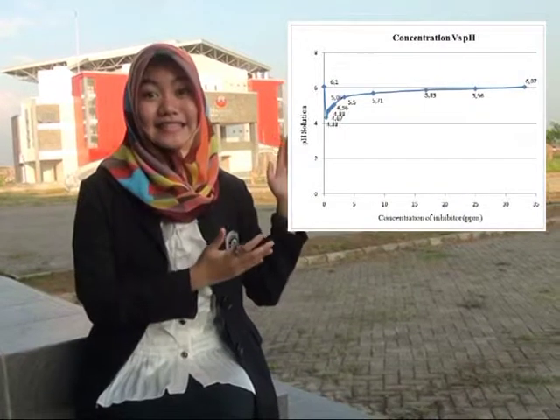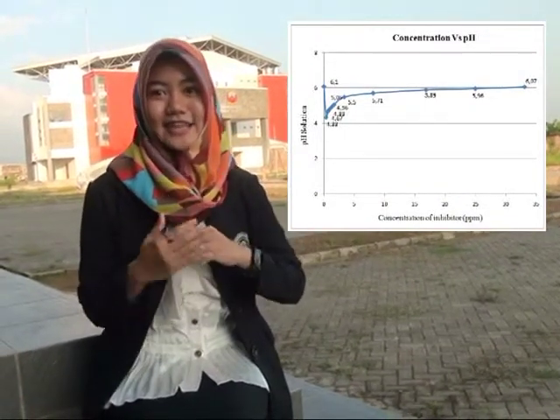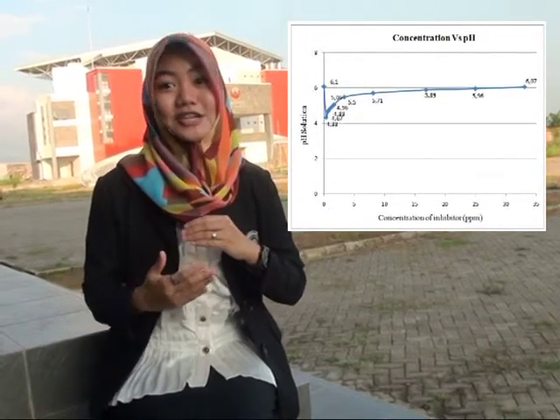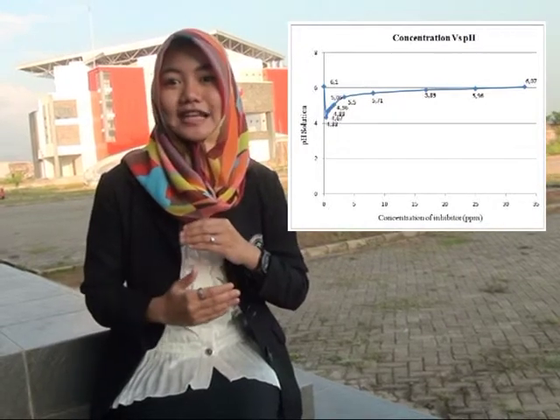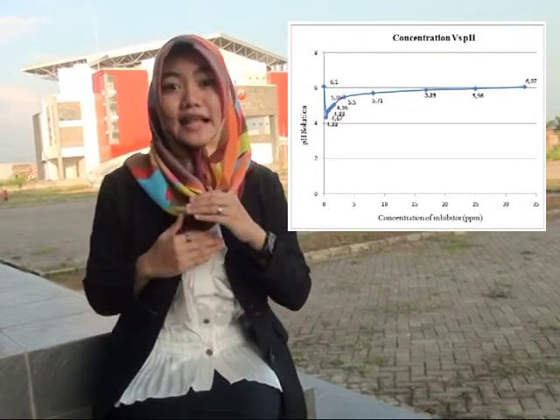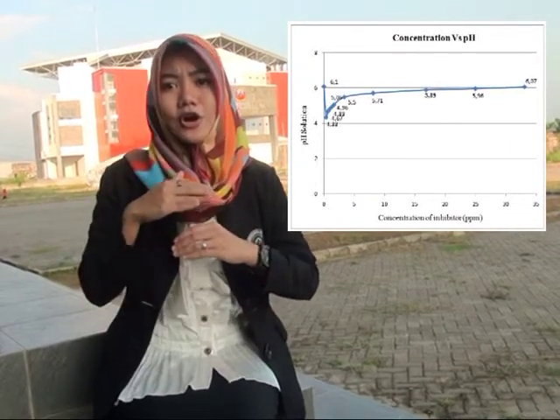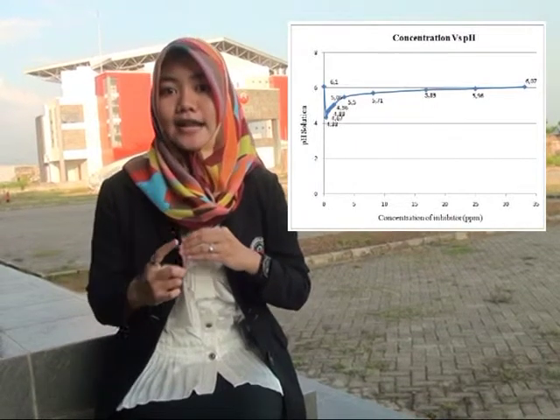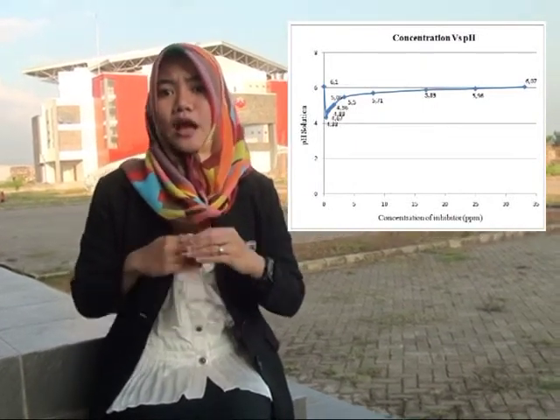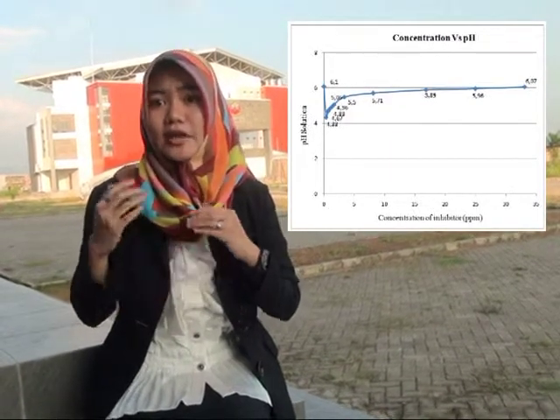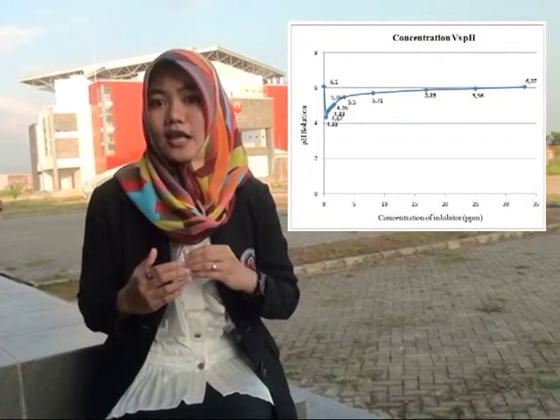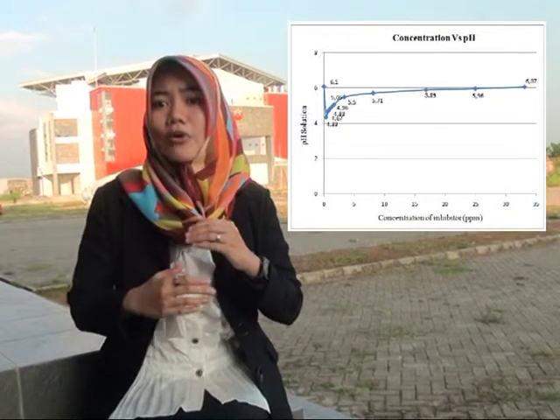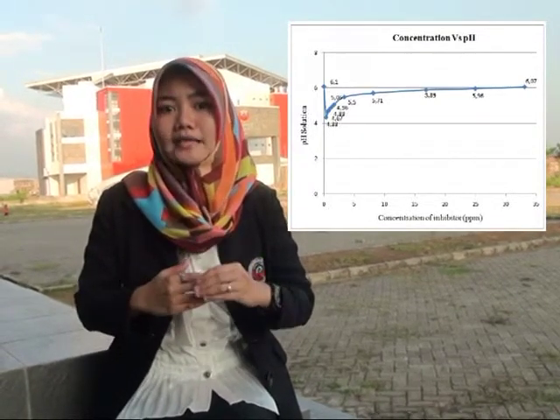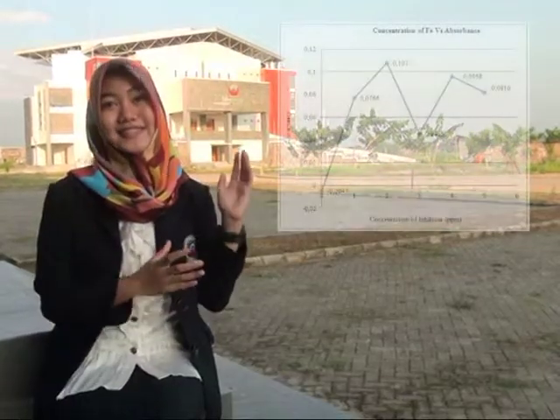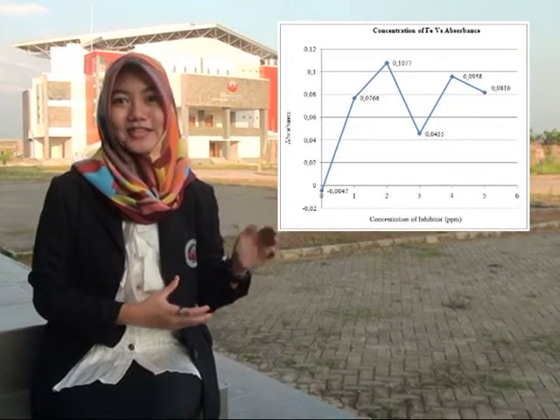as at this concentration a perfect layer had formed, marked with the closing of the entry surface of the metal steel samples. The third chart explains the potential hydrogen value of various concentrations of aloe vera inhibitor solution. Potential hydrogen is one of the factors that influence the corrosion rate of mild steel. The lower the potential hydrogen, the greater the possibility of the metal to corrode, because the metal decomposes into metal ions in an acidic environment. With the addition of the inhibitor, the potential hydrogen of the solution can increase, so that the corrosion rate of the mild steel will be reduced because the steel will form a passive film on the surface.